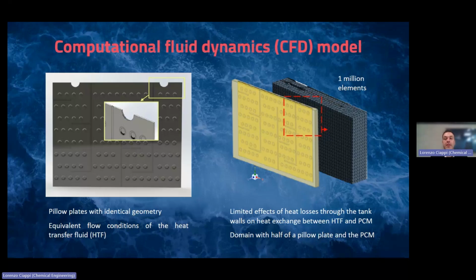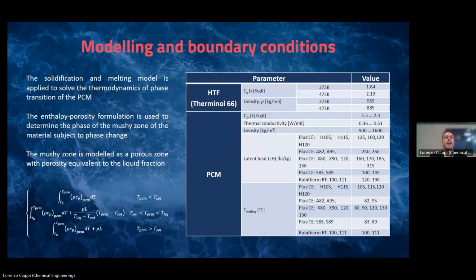An unmapped mesh was created using 1 million elements, performing a sensitivity analysis from a value of 0.3 million to 3 million elements. The solidification and melting model was applied to solve the thermodynamics of the phase transition of the storage material, and an enthalpy-porosity formulation was applied to determine the phase of the mushy zone. The heat transfer fluid is Therminol 66 due to its good heat transfer properties, while different typologies of phase change materials